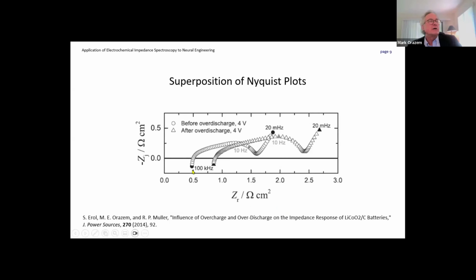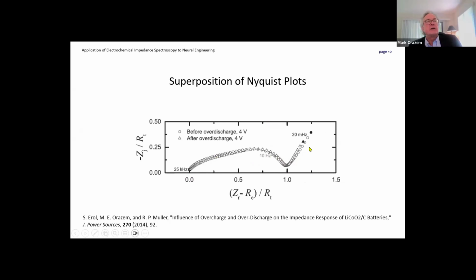This is an example from our work on lithium batteries. In this one experiment, we over-discharged the battery to 2 volts, and then we waited for 2 days while the battery sort of returned from a very high impedance situation to an impedance situation that looked very similar to what we began with. In this particular case, we decided to scale by the resistance at the end of this capacitive loop. And what we can see is that we were able to superpose those data as well. Again, showing that after an over-discharge excursion, the battery chemistry did not change.